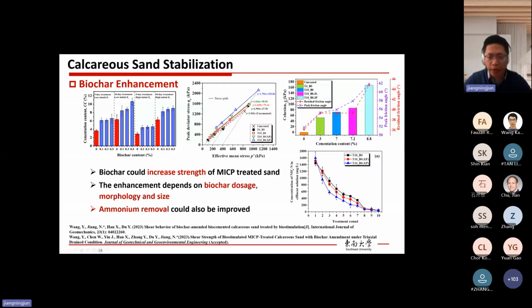So these results demonstrate how biochar can help increase the strength of calcareous sand. Now, in addition to the strength improvement, the biochar could also help to absorb some ammonium. This graph shows that during the several cementation solution treatment procedures, we monitored the ammonium concentration within the effluent. The blue one shows the sample with powder-shaped biochar. The red one shows the sample with needle-shaped biochar. And the black one shows the sample without biochar.